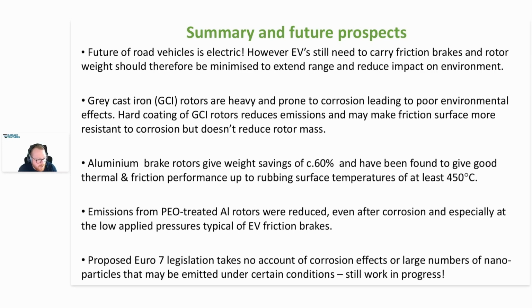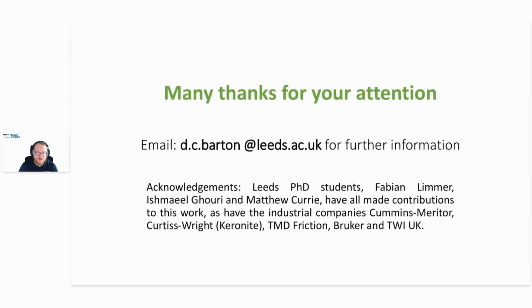Aluminium rotors give significant weight saving at moderate additional cost and have been shown to give good friction and thermal stability up to moderately high surface temperatures. Emissions from the PEO coated aluminium rotor were reduced, even allowing for the effects of corrosion. The Euro 7 legislation takes no account of the effects of corrosion or the large number of nanoparticles that can sometimes be emitted, which are the most dangerous from a health point of view. There is still much work in progress.